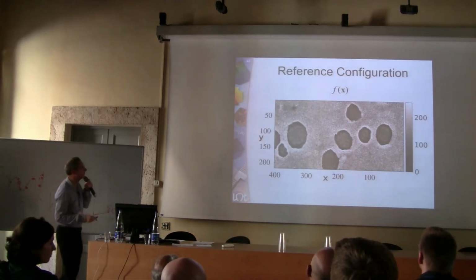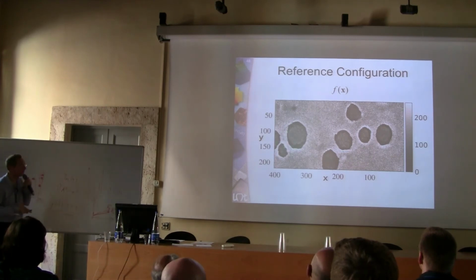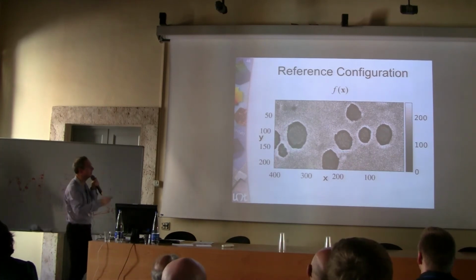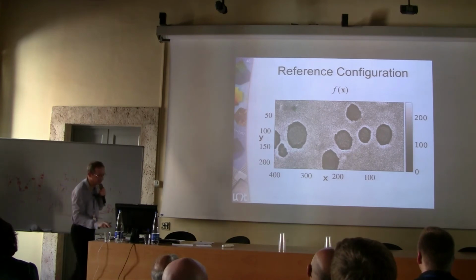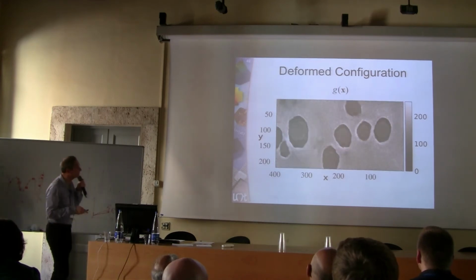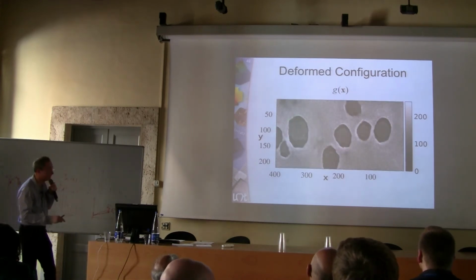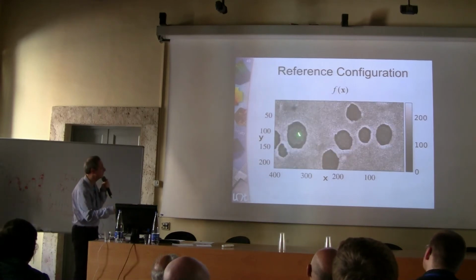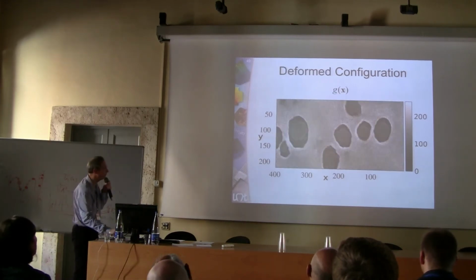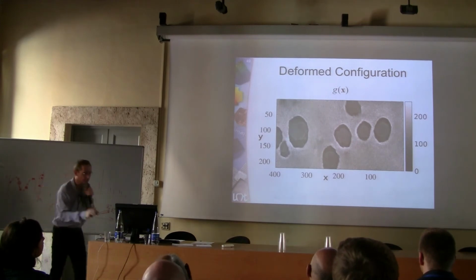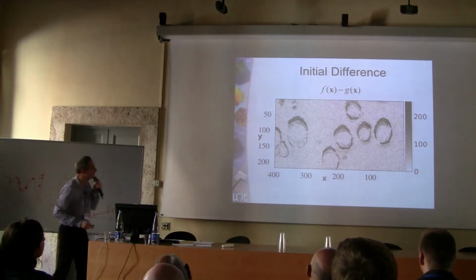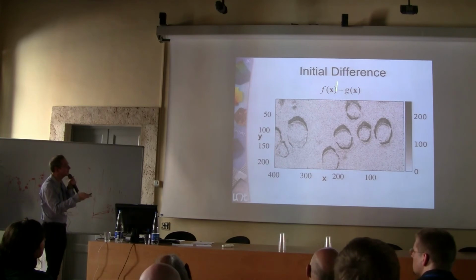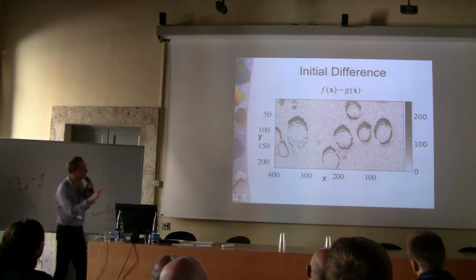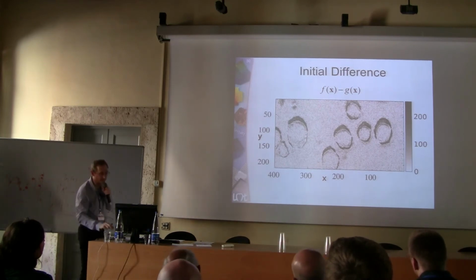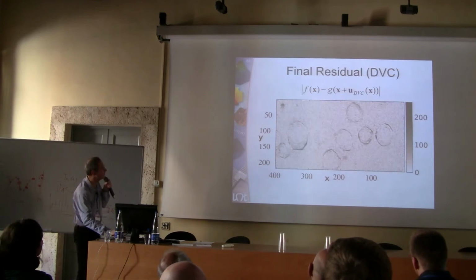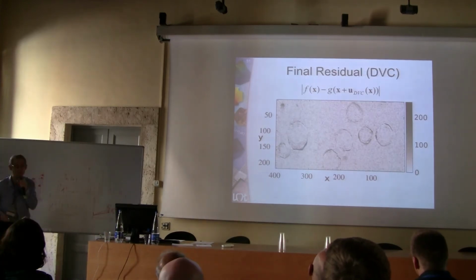Okay, so just to illustrate what I'm talking about, this is a section of the volume in the reference configuration, in the deformed configuration, and here you see that you had some debonding that occurred. Remember, that's what we saw - or you have to trust me - that's what's seen in the residuals. That's the raw difference that you do with the two volumes, so you didn't correct for any kinematic quantity, and that's at the end of the registration process.